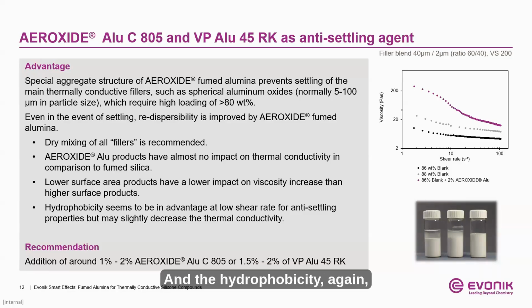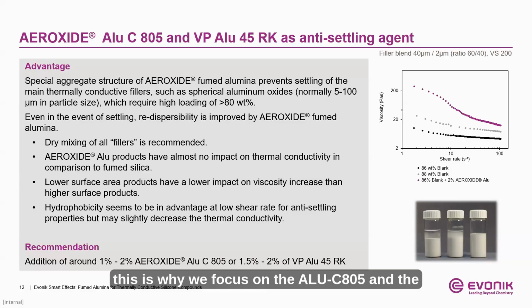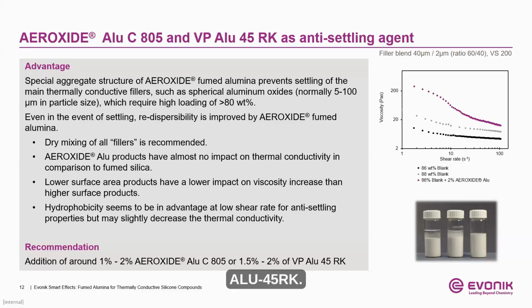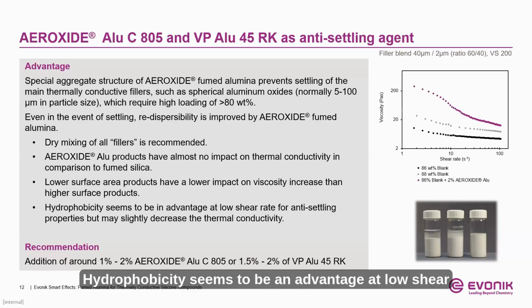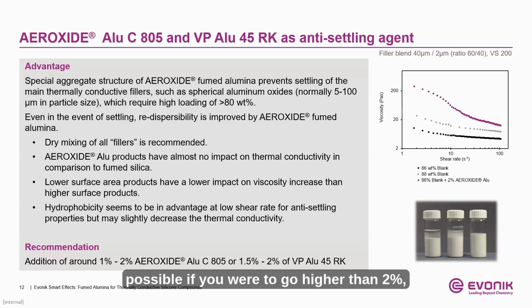And the hydrophobicity, again, this is why we focus on the ALU-C805 and the ALU-45RK. Hydrophobicity seems to be an advantage at low shear rates for anti-settling properties. It may slightly decrease the thermal conductivity. We didn't see that too much here today at 2% loading levels. It's possible if you were to go higher than 2%, you may see a bit of a drawback, again, but only slight and not nearly to the degree that the fumed silica, again, would detract from thermal conductivity in these studies.